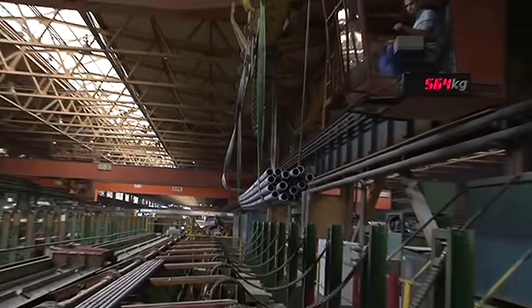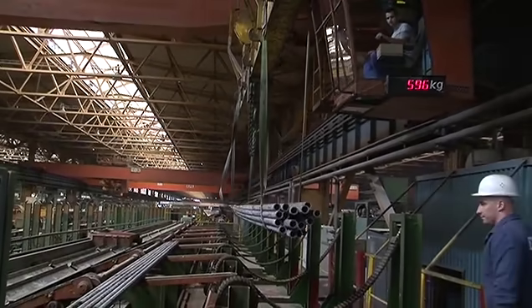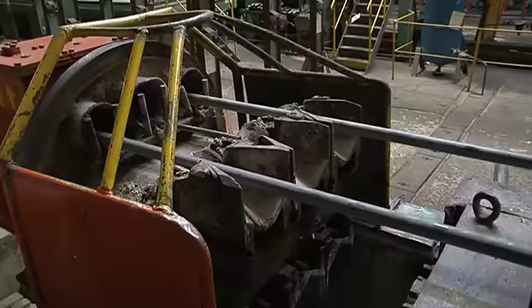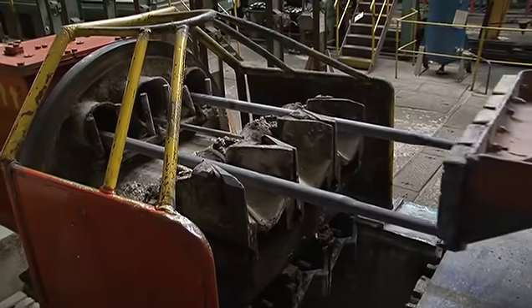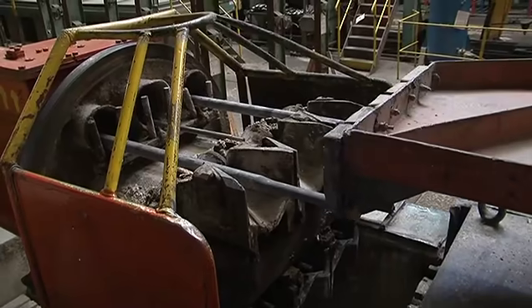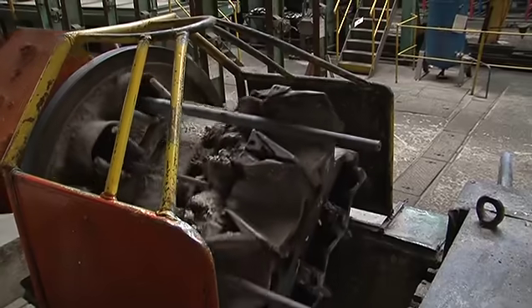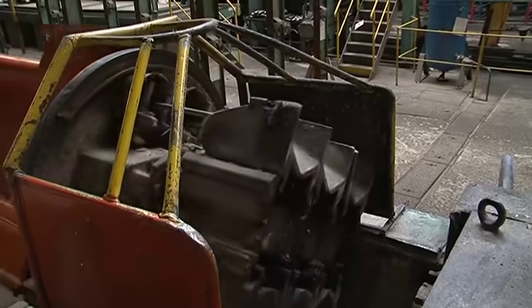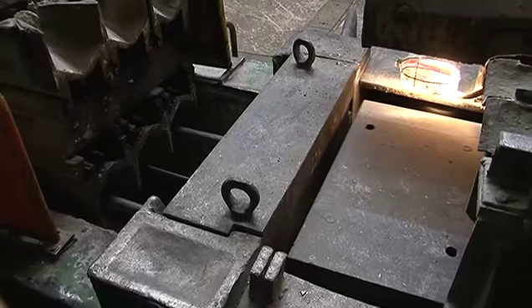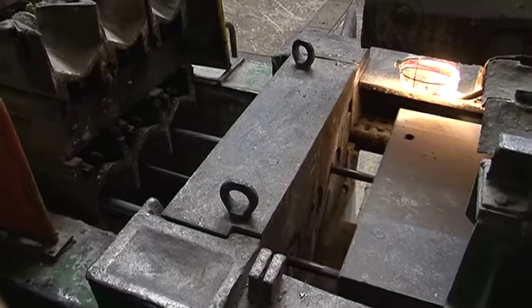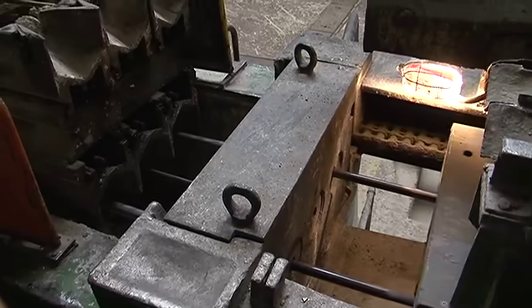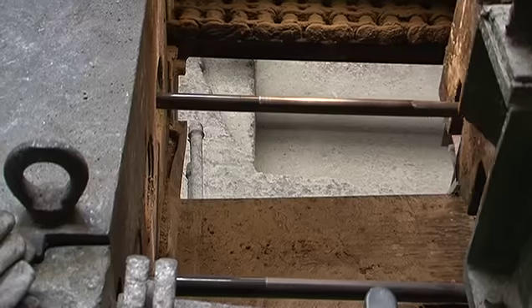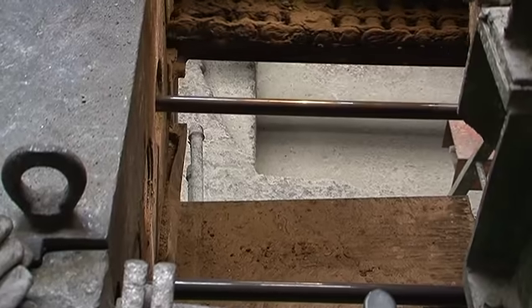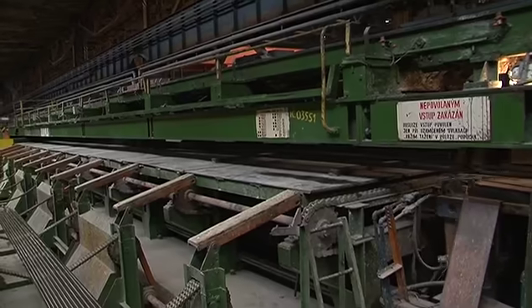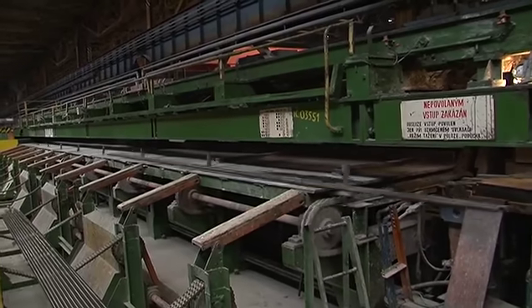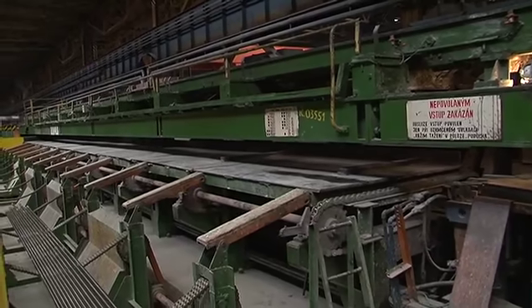By cold forming on the linear drawing benches, using a die plate or mandrel, this changes the dimension of the original tube. For example, to achieve the smallest diameter of 3 mm, it is necessary to draw the original pipe with a diameter of 32 mm up to 9 times. The device during this process develops a pulling force equivalent to that of 10 railway locomotives.